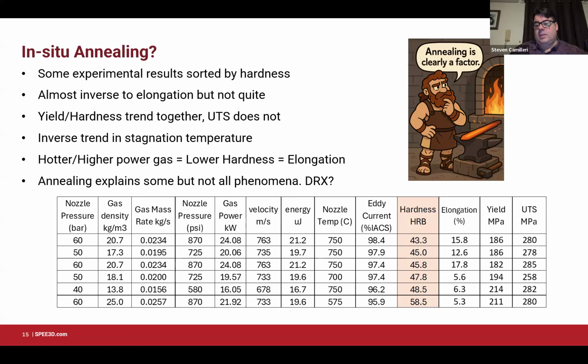Yeah, so the yield strength and the hardness do correlate extremely tightly, which is relatively expected. But it's a good point. If there's more work hardening in the material, we would expect to see a higher yield and less elongation, leading to roughly the same UTS. I just didn't expect the UTS to change so little through this whole random test matrix. It's shockingly stable.